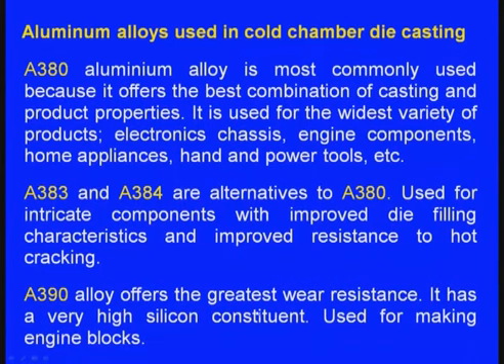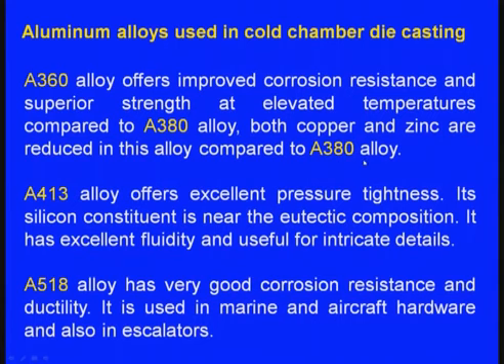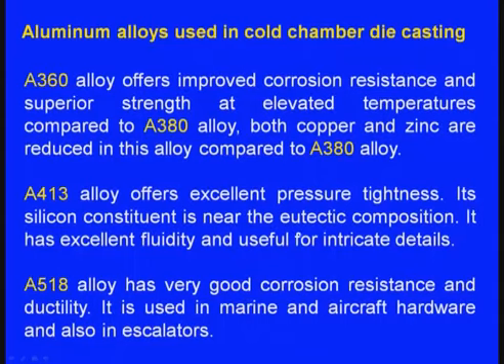A390 alloy offers the greatest wear resistance. It has a very high silicon constituent and is used for making engine blocks — the high silicon proportion enhances fluidity and wear resistance. A360 alloy offers improved corrosion resistance and superior strength at elevated temperatures compared to A380. Both copper and zinc are reduced in A360 compared to A380. A413 alloy offers excellent pressure tightness — its silicon constituent is near the eutectic composition, giving excellent fluidity and making it useful for intricate details.